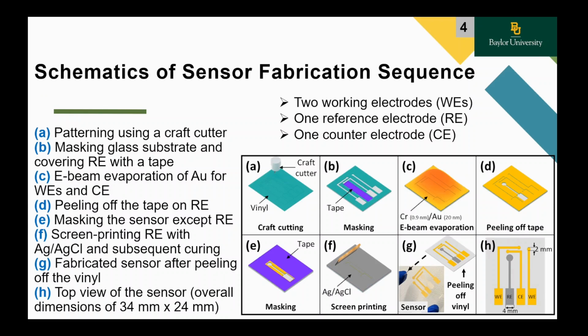So the sensor design consists of two working electrodes, one reference electrode, and one counter electrode. The fabrication process began with designing the electrode pattern, which was cut on the vinyl sheet using a craft cutter. Next, the sensor design was transferred to a glass substrate by attaching the adhesive vinyl pattern as masking and covering the reference electrode segment with tape. After that, the material deposition of the working electrode and counter electrode was completed with gold deposition using an electron beam evaporator.